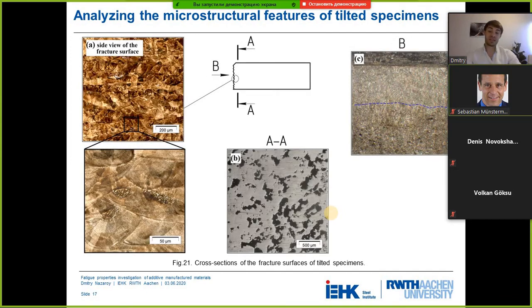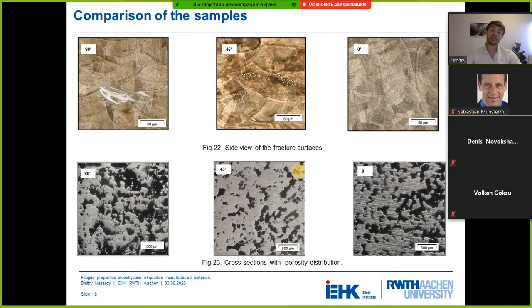And with regards to the tilted specimens, on the side view of the fracture surface, we see a morphology something between columnar grains and equiaxed grains. With regards to the porosity, it showed the smallest amount of porosity in comparison to vertical and horizontal specimens. All of these features resulted in the crack propagating in an intermediate fashion. On this picture, I listed all of this microstructure and porosity distribution in order to better understand how the building orientation influences all of these parameters.